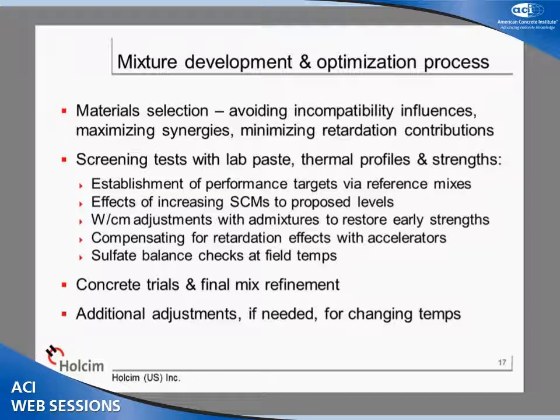And we'll do this through initially increasing the SCM level, and then we might actually need some additional admixtures in order to reduce the water cementitious ratio for early strength development. Side effects from that may be additional retardation that needs to be compensated for with accelerating admixtures and so forth. So here's how that goes.